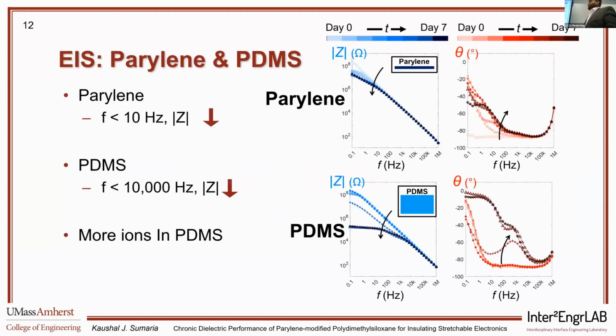So we look at our experiment results. We see that the parylene layer we have demonstrates behavior closer to an ideal dielectric behavior, whereas the PDMS layer that we have captures the ion percolation process similar to what we show in the diffusion model. These 2 are our reference samples so that we can test the layers individually before we test the combined layers.